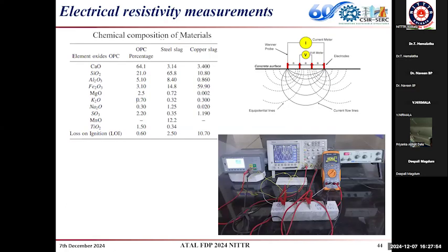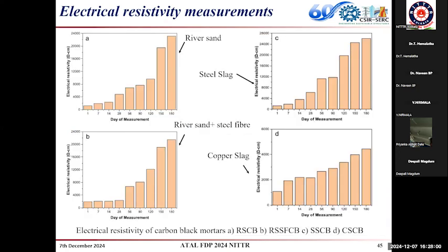So these are some of the test setups we have made for measuring the electrical conductivity. This is just to see, when we are adding conductive material, how it improves the conductivity. It is measured in terms of resistivity. When resistivity decreases, the conductivity increases. If you see the scale here, it is 24,000, here 6,000, and this is 8,000. So it shows that the electrical resistivity is reduced by 1 order when we are using copper slag.